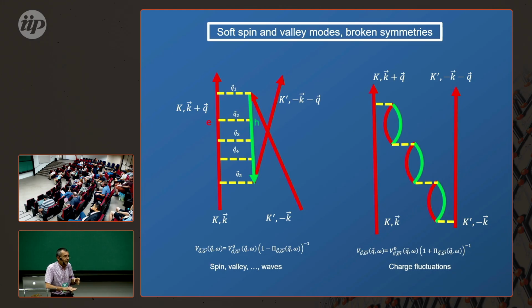And in addition, it's too bad he's not here, if you ask Andrei Bernevig whether his topological Kondo model works for a twisted trilayer, which is not symmetric, or a twisted double bilayer, he will probably tell you it doesn't work. So there is a relation. You can either say that the strong Hartree potential is a proxy for how large the critical temperature is going to be, or the validity of the twisted Kondo system is a different proxy, but basically equivalent for the existence of superconductivity in twisted systems.